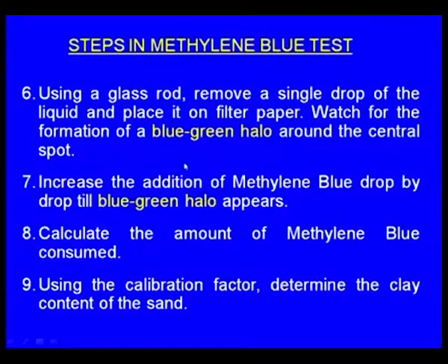If we do not see the blue green halo, increase the addition of the methylene blue drop by drop till the blue green halo appears. Once this blue green halo appears, we have to stop dropping the methylene blue solution. Now, we have already calibrated between the methylene blue solution and the clay content.